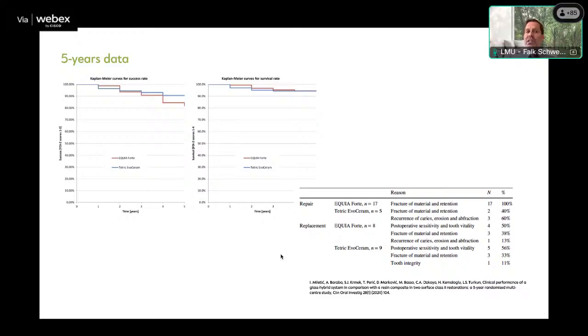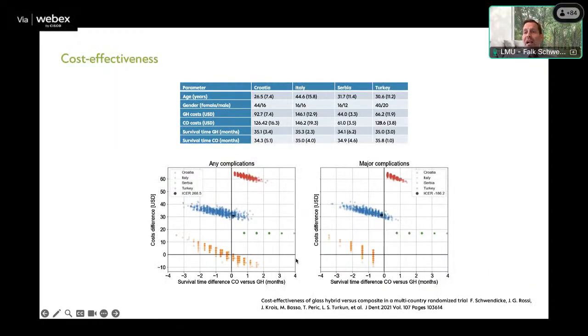This is the 5-year data, and you can see that for survival, so the restoration surviving, the survival curves are still roughly the same in the middle there in that graph. For success, including those cases where you can maybe repair the cases, we see that over 5 years we get a little bit more failures in the glass ionomer group than in the composite group, and that's also highlighted here in the table. The majority of failures, if they occurred in the glass hybrid group, were repairs, where you can manage the margins in some kind of way, but you don't need to exchange the whole restoration, which of course from a clinical perspective is very important, but it's also important from a health economic perspective.